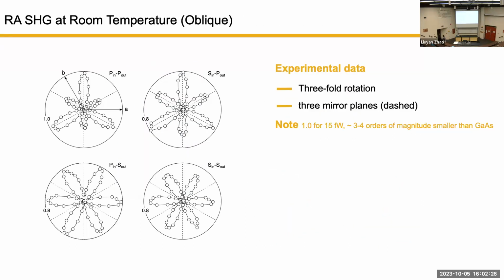Our measurement was this so-called RA-SHG, and we do it in all four polarization channels, P in, S out, and so on and so forth, four channels. So by the combination of these four channels, we clearly see the required threefold rotational symmetry. And the dashed lines are the mirrors. Clearly we see for all of them, we have three mirrors.